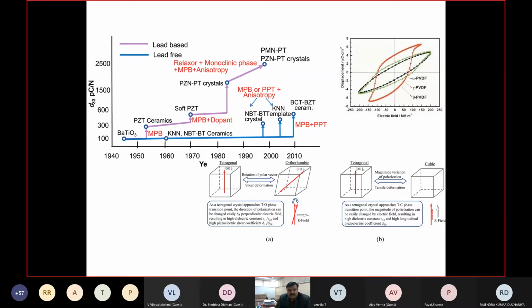So here you can see the line in purple color, that is for lead based materials, and the line in blue color, that is for lead free materials, right? So you can see here that still the lead based materials have high D33 coefficients, but the lead free are nearly 4 times lower than that of lead based materials, right? So that's why this particular area of lead free ferroelectric materials is a novel area in which people are working tremendously to increase the D33 coefficient similar to that of the lead based materials, right?